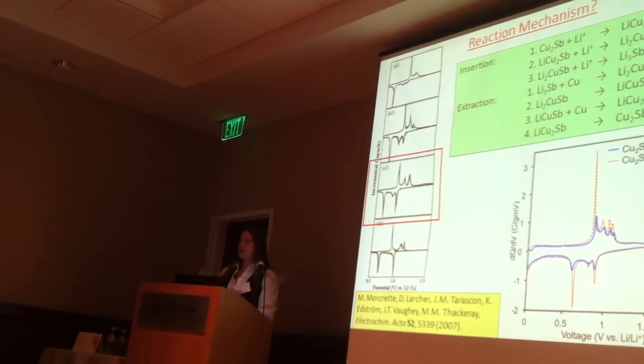It's got this incredible cycle life due to not only the presence of the aluminum oxide improving the charge transfer, but also because of the small particle size that we think is fundamentally changing the way this material, this alloy, reacts with lithium.